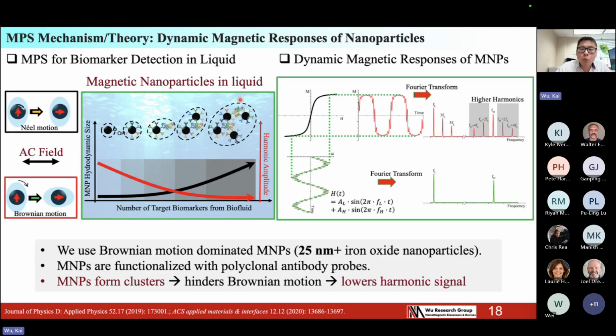This clustering will block the Brownian motion of particles. Imagine you have nanoparticles. You apply an AC magnetic field to switch up and down. The particle will try to realign its magnetic moment to the field through the joint Néel and Brownian process, as I show in the left figure. After the cross-linking of particles in the presence of the analyte, the clusters will block the Brownian motion of particles, which will lower the dynamic response of particles to the magnetic fields.